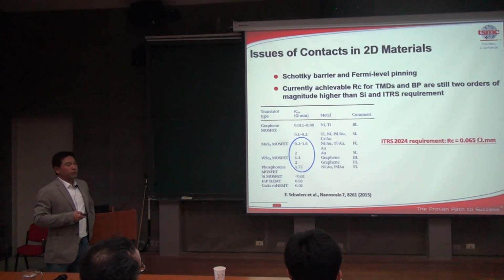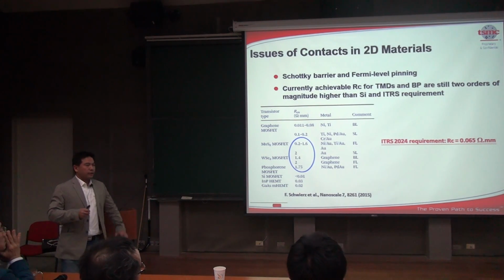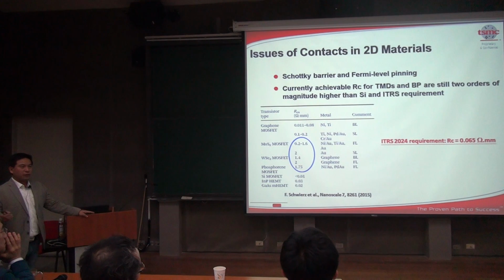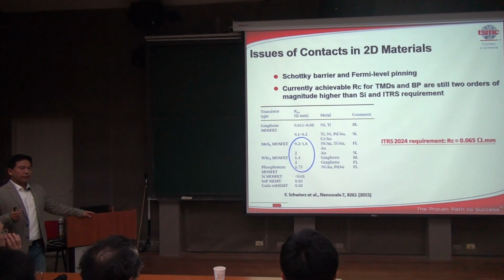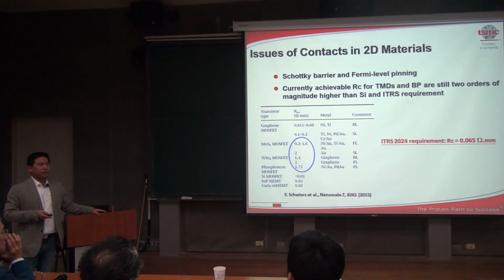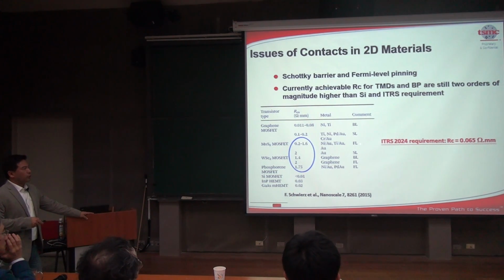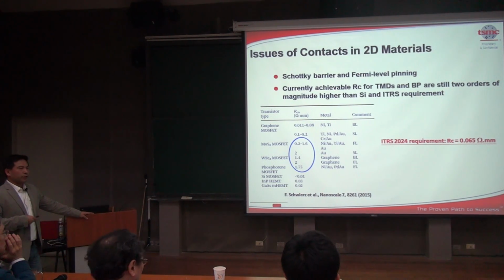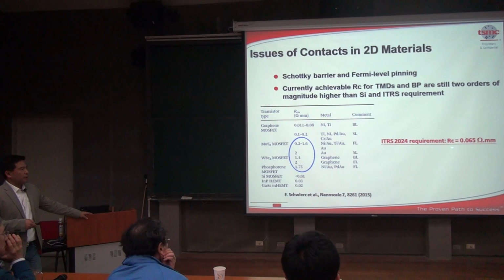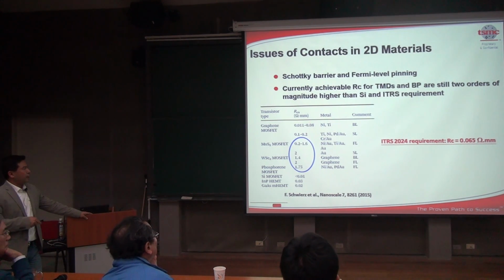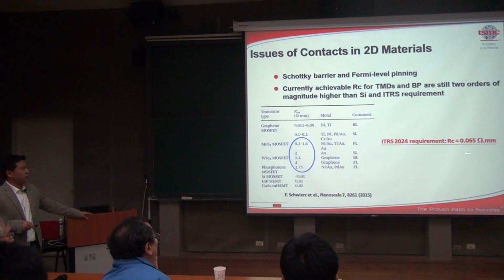Another issue that's common in 2D materials is the contacts. Remember that in transistors, in the on state, the current will flow through the transistor, but if you have a large contact resistance, then it will become the limiting factor. The ITRS roadmap, this is the industry projection of what the device characteristics should be in the future, calls for a contact resistance of 0.06 ohm per millimeter, or like 65 ohms per micron. In graphene, you can get to a value that's quite close, but in other 2D materials, MoS2, phosphorene, they're still 2 orders of magnitude larger than this industrial requirement in 10 years.